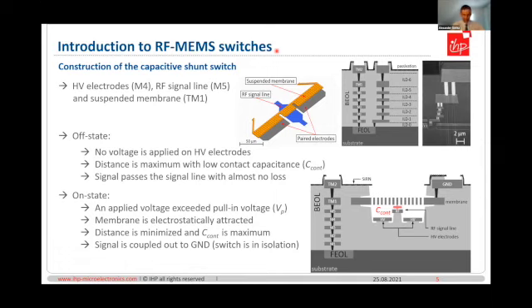In detail, the switch consists of high voltage electrodes, which are designed in metal 4, the RF signal line in metal 5, and the suspended membrane in top metal 1. As you can see, all parts are integrated in the upper part of the 7 metal layer backend of line. Here is a schematic, and here is an SEM image. In the cross section in this schematic you also see the HV electrodes, the RF line, and the top metal 1 membrane.